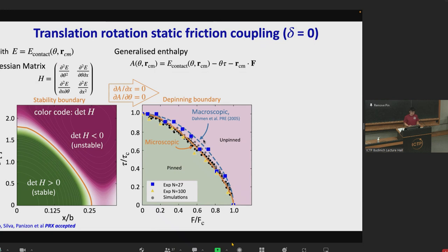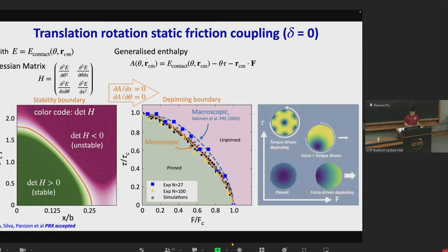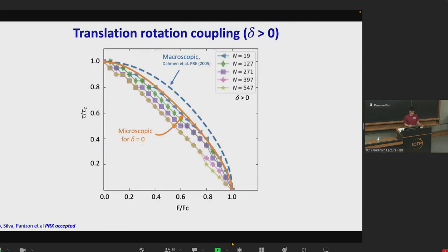The difference between the microscopic and macroscopic cases is not large, but the mechanisms are fundamentally different. In the microscopic case, when the cluster is pinned, there is a large moiré pattern centered in the cluster. When you try to depin the cluster, this large moiré spot in the center has to move out through the cluster's edge. When a torque is applied, the low-energy moiré spot becomes significantly reduced in size, making it much easier to pull it out of the cluster's edge and therefore reducing the static force. This is also the translation rotation coupling for the case where the two surfaces have different lattice spacings, and the difference between the microscopic and macroscopic models becomes larger in that case.